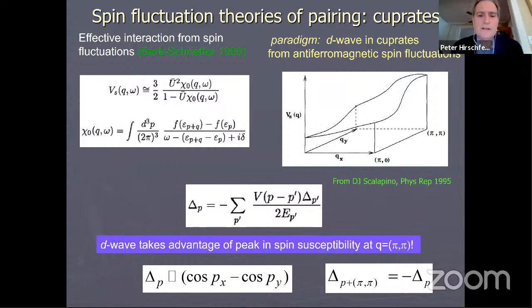In the mid-60s, it was thought that this could lead to the suppression of TC from spin fluctuations, because the susceptibility is typically peaked at Q equals zero for a screened Coulomb interaction. But if you have a Fermi surface, which has a special structure, you can get other results. And so this is the standard picture for the cuprates of the magnetic susceptibility or the effective spin fluctuation pairing interaction as a function of momentum Q.